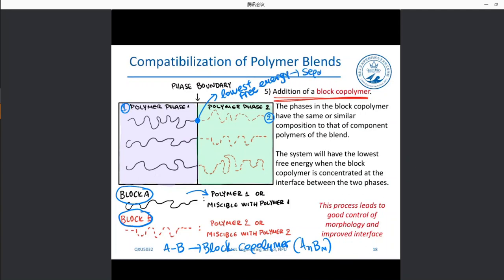So we have a separation of blocks at the interface. What we need is the block copolymer to be concentrated at the interface between phases. So this is an AB diblock copolymer. You can see the A block residues in this phase, and B residues in this phase, and this places essentially covalent bonds here. We have the formation of covalent bonds.